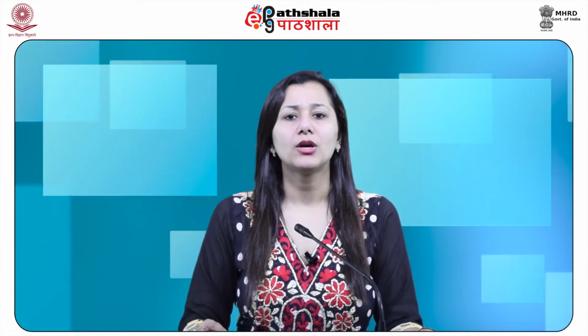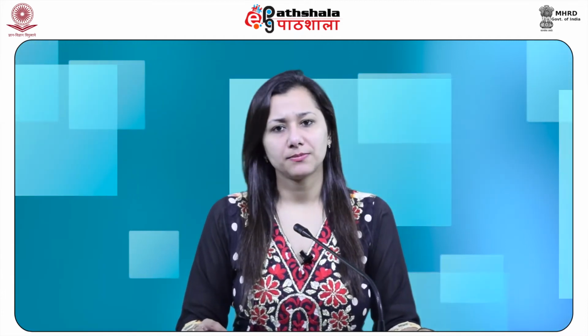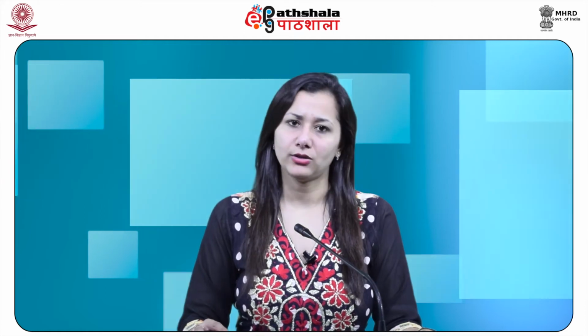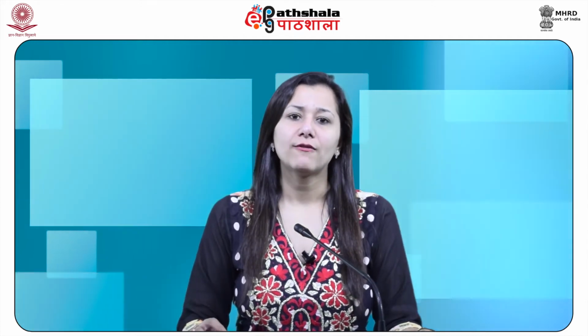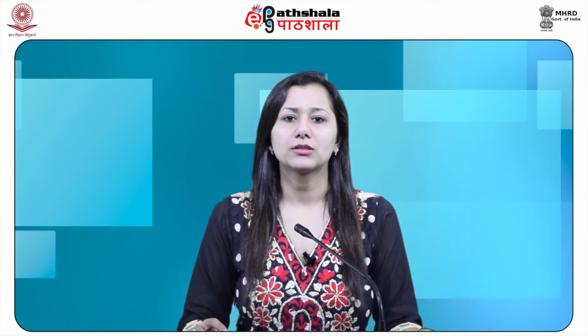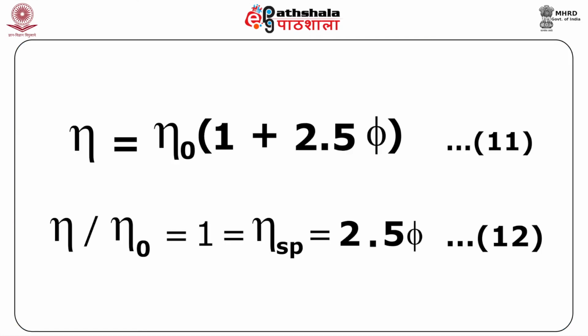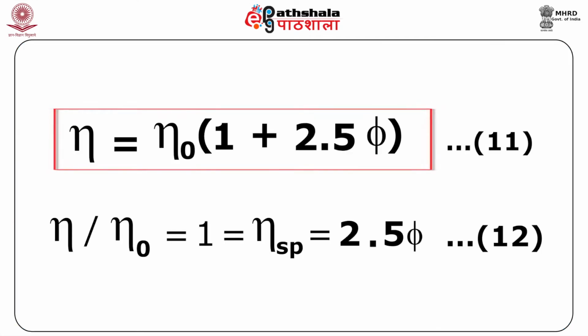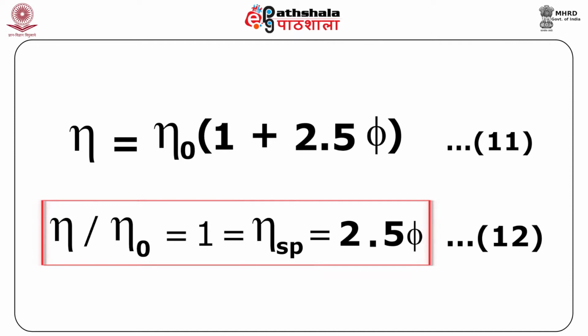In 1906, Einstein derived a relation between the viscosity of dilute suspensions of hard spherical molecules and the volume fraction phi of the solute molecules. This is given by equation 11 as eta equals eta naught into 1 plus 2.5 phi. Rearranging the equation, we get eta by eta naught minus 1 equals eta sp equals 2.5 phi, as equation 12.